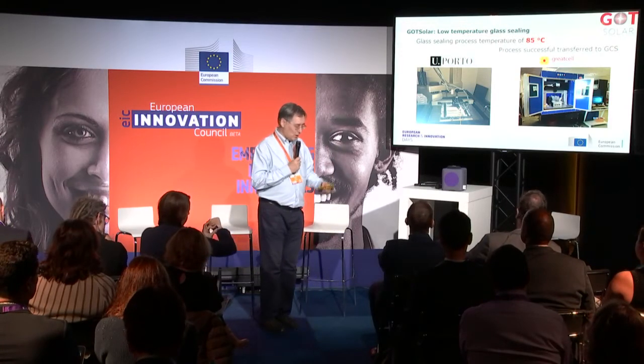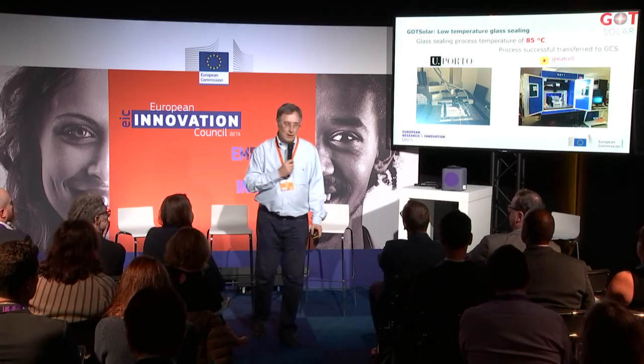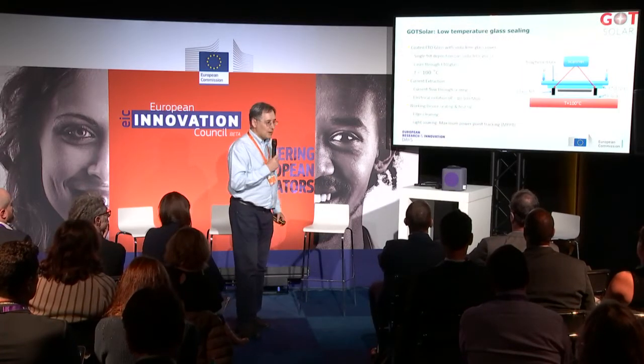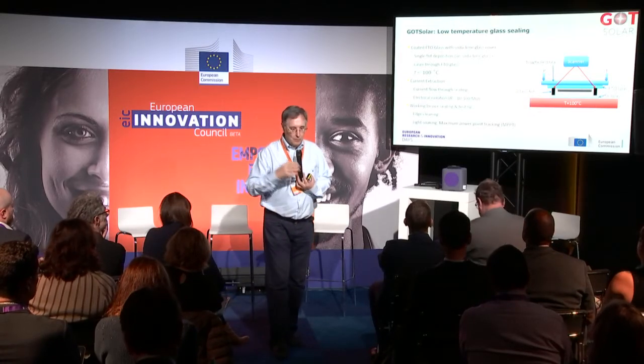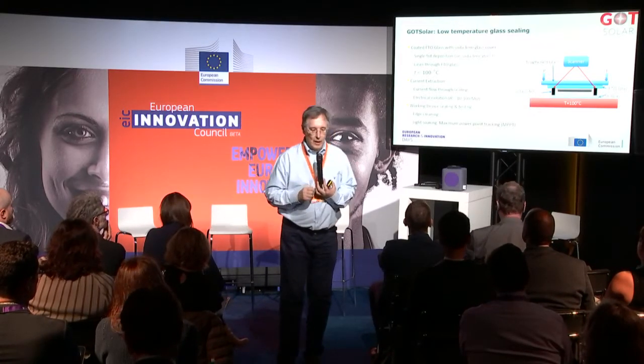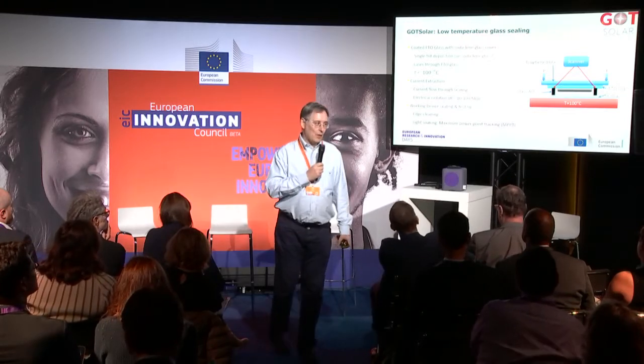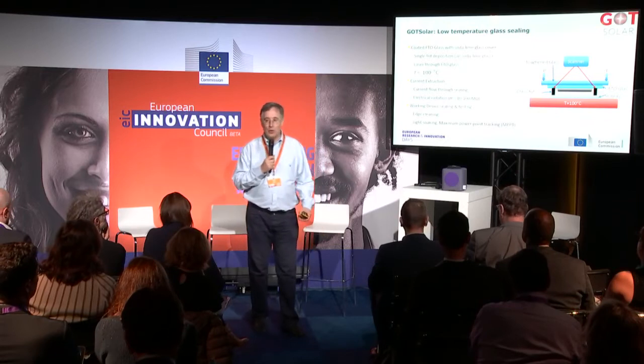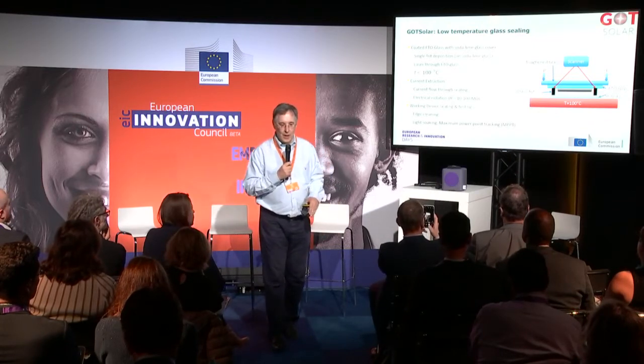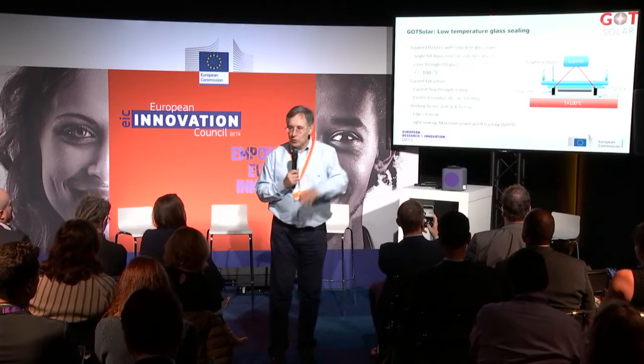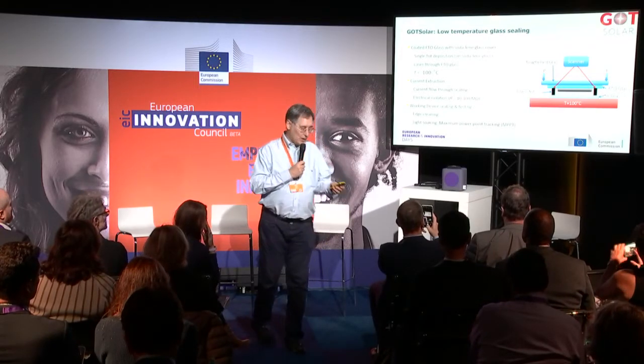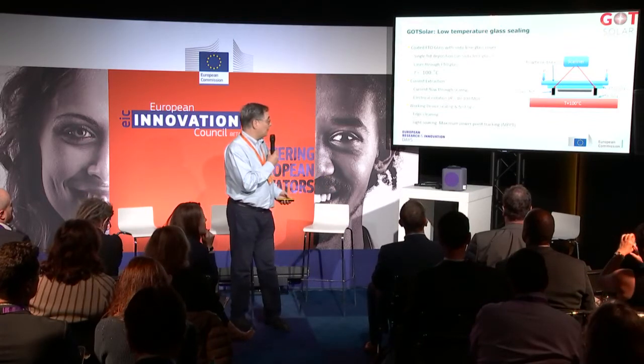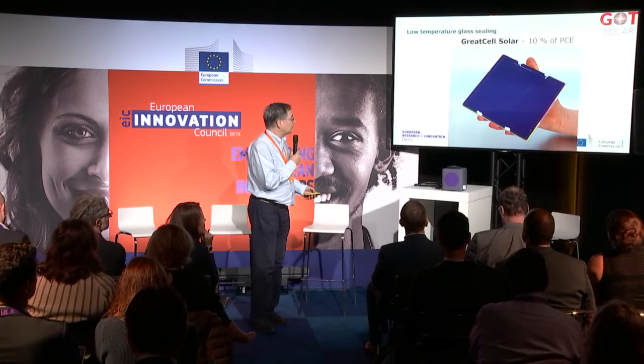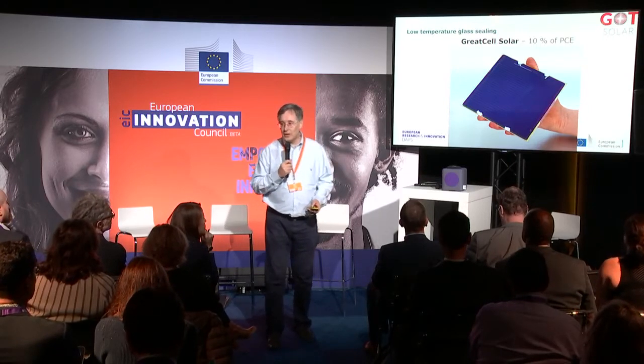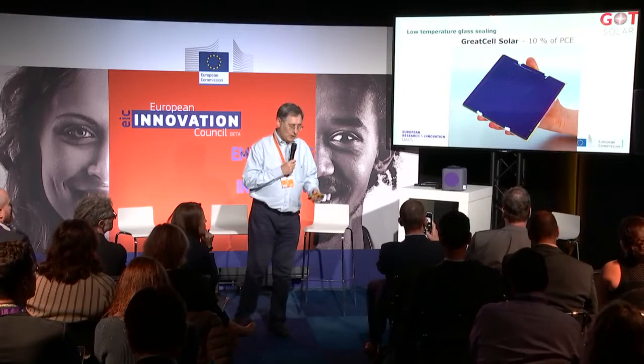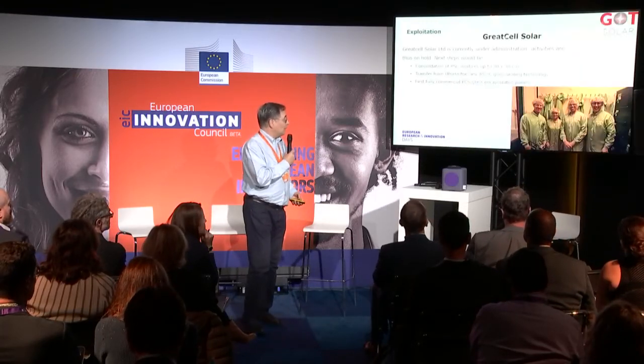And now we can go as fast as 1 centimeter per second on glass sealing. And moreover, we can put the glass sealing line just on one side of the substrates, the one that is going to cover it, because the other substrate is free to deposit all the layers necessary for the photovoltaic cell. This was really possible. So now you can see already a nice device that is almost ready for going to the market. And there are several companies.